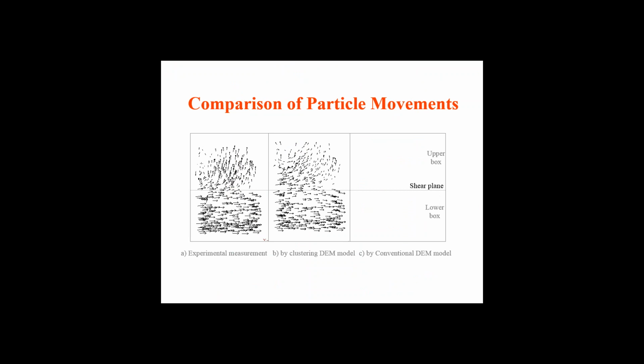The cluster one. See this experimental measurement, and this is a cluster DEM approach, considering the particle shapes in there. And these patterns are very close. And with this conventional approach, you will see the movements are scattered everywhere. And that means not consistent with experimental measurements in there.